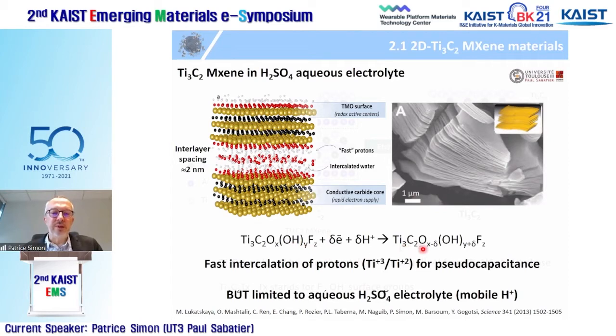This is what we did more than a couple of years ago, in 2013. We studied the electrochemical behavior of MXene Ti3C2 in sulfuric acid electrolyte. And what you can see is that if you polarize your Ti3C2 MXene in sulfuric acid electrolyte, if you inject electrons, then you are going to intercalate cations, and this cation intercalation together with electron injection results in the change of the oxidation state of the titanium. And you end up with a very fast proton intercalation, a change of titanium redox state, and then you end up with a redox reaction with no diffusion limitation within these 2D slits.